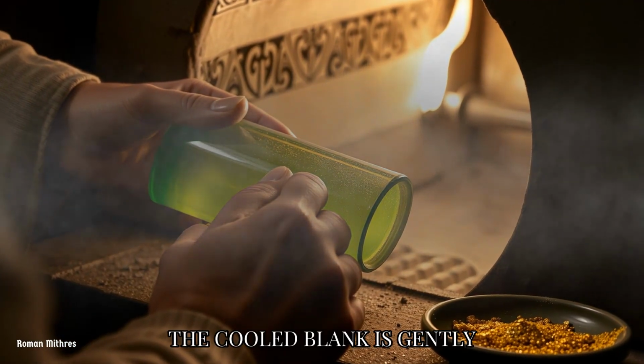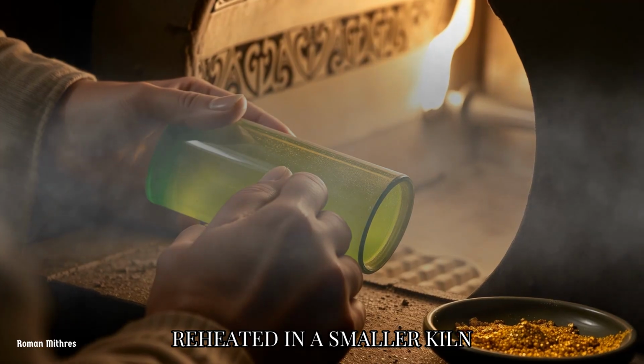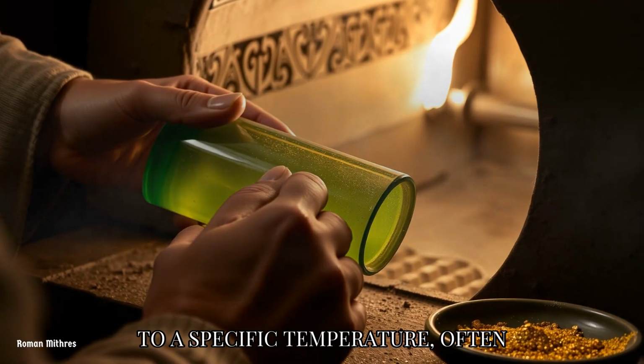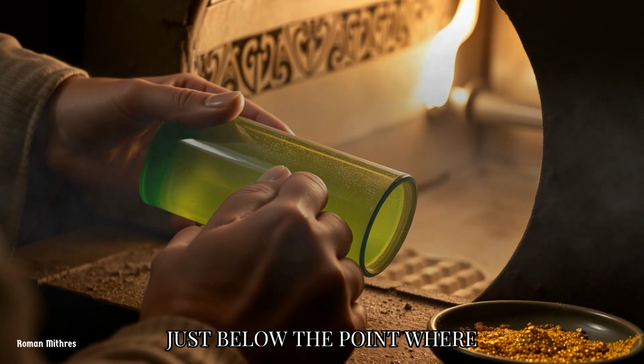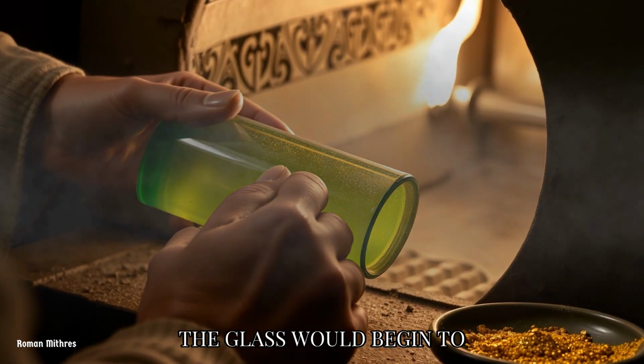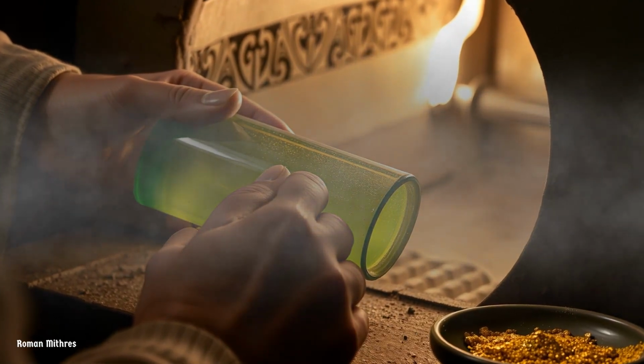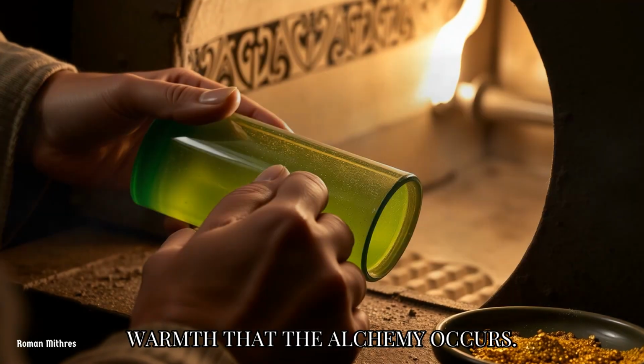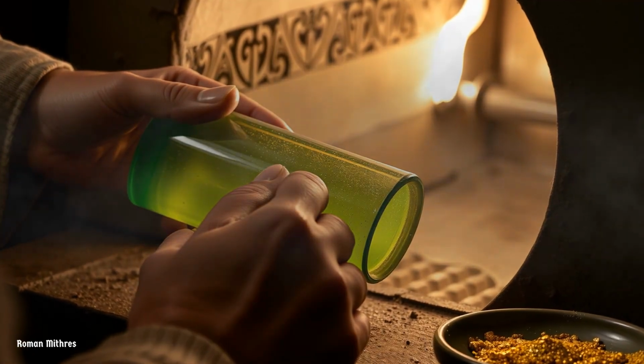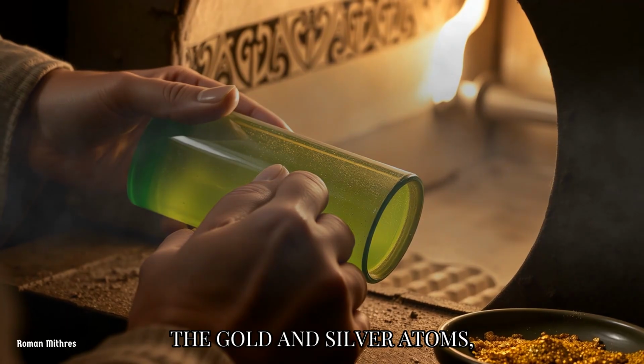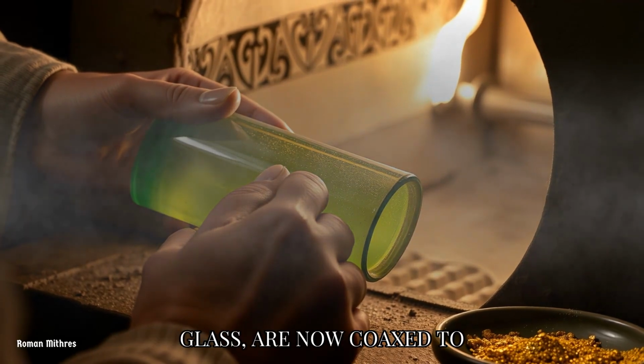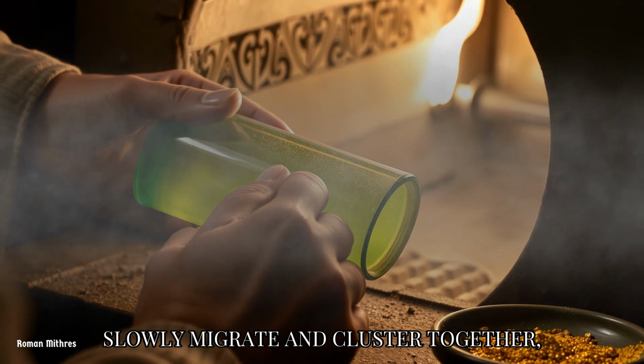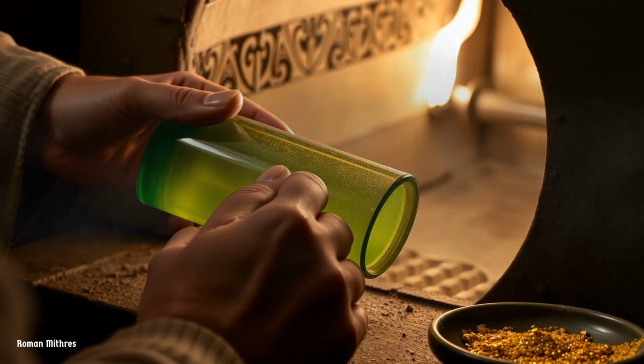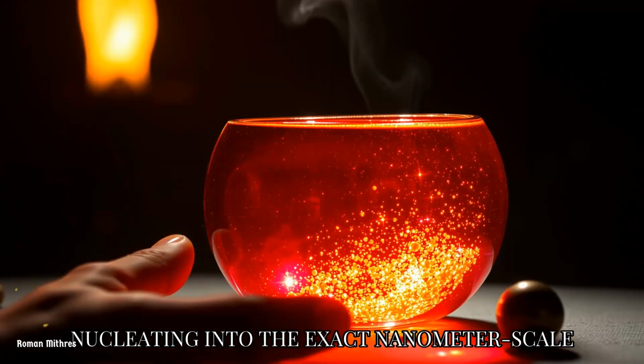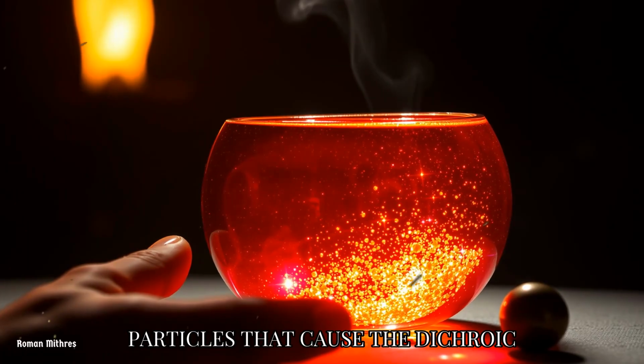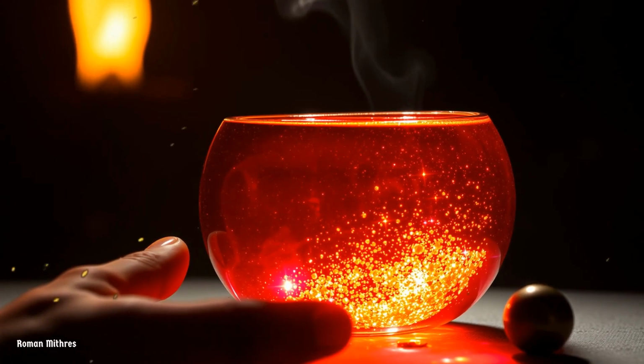The cooled blank is gently reheated in a smaller kiln to a specific temperature, often just below the point where the glass would begin to soften and deform. It is in this gentle warmth that the alchemy occurs. The gold and silver atoms, which were dissolved throughout the glass, are now coaxed to slowly migrate and cluster together, nucleating into the exact nanometer scale particles that cause the dichroic effect.